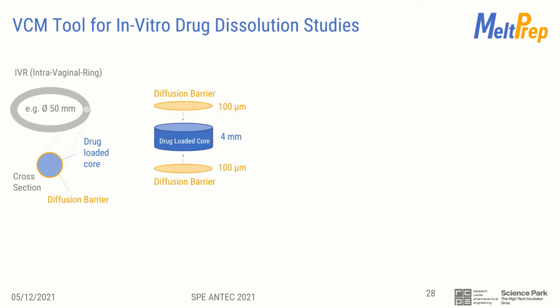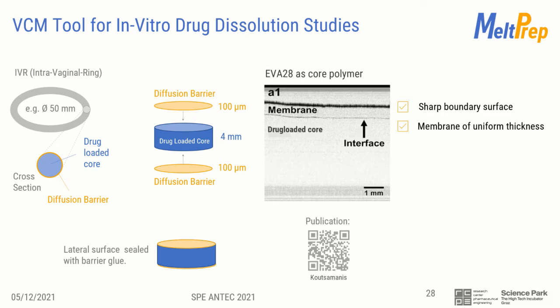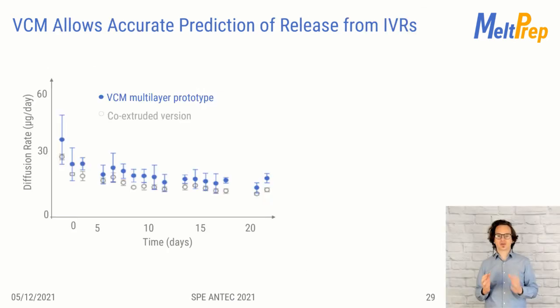The final VCM sample that they used was a sandwich of 2 100 micrometer thin diffusion barriers filled with a drug-loaded core. Then they covered the lateral surface with barrier glue, used optical coherence tomography to check for interfaces and see if diffusion barriers are uniform in thickness. Afterward, they subjected the sample and the co-extruded version to dissolution. In the dissolution curves, you see a good match of VCM and the co-extruded samples.